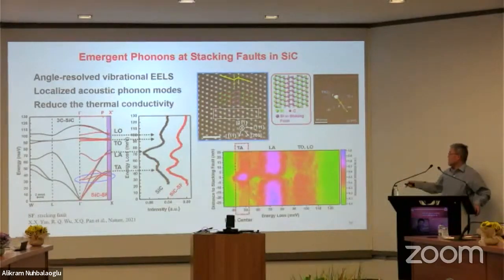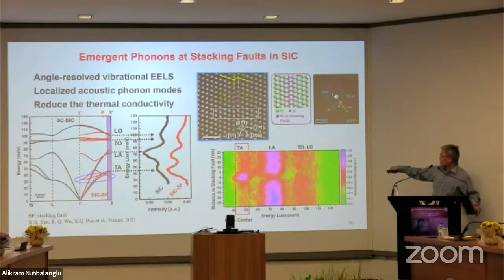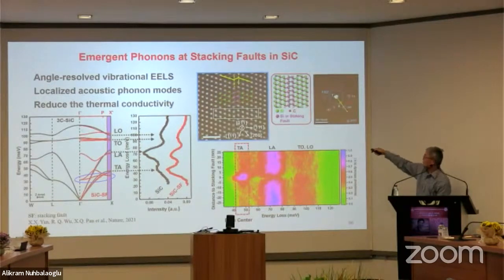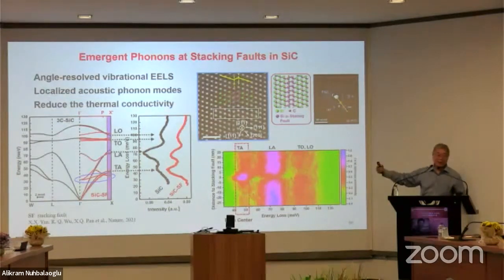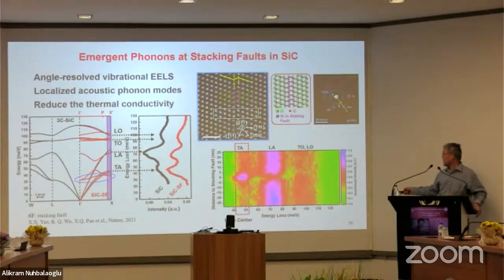And it will be much easier to understand using imaging. You can see that this is the image you take at about 90 degrees. So this is a position. This is a position. Here's the interface. Okay, the interface is here. And then this is an energy-position map. The color indicates the intensity, how many phonons at a given energy. You can see that at the interface, this TA mode appears as a new mode, and the existing TA mode and LA mode in the silicon carbide is significantly suppressed in this region and form the new mode. That means there's a new amount of new phonon existing at the interface. That's a single stacking fault. And then we also analyze details.